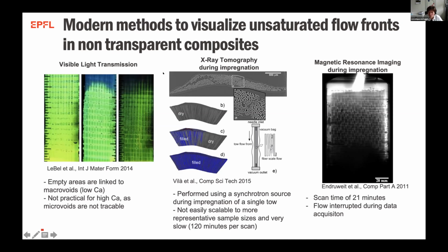You can do it by X-ray tomography, of course. But the problem with X-ray tomography is, this was done with a synchrotron source. It's work by our colleagues in Madrid, but they took 120 minutes per scan. So if you go really fast, of course, the flow front has gone way, way beyond. So you have to make a kind of weird impregnation. And they did recently a new paper where they improved this a bit, but still it's a bit limited. And then some other people tried with magnetic resonance imaging, and there they had a scan time of 21 minutes, but they also got some interesting results.